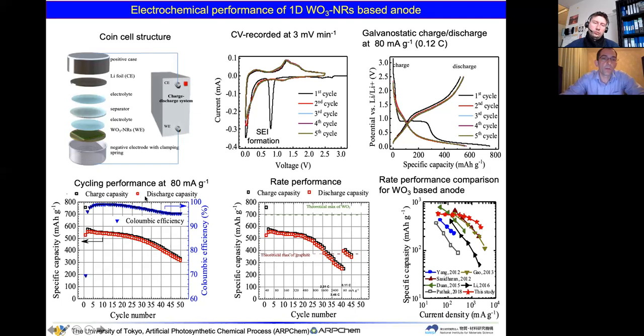The cyclic performance at this 80 milliamp per gram. So it's relatively a stable material during the cycle number. However, there is a small degradation rate. But this is interesting, okay? If we look on this graph, we can see that if we change the C rate to the smaller one, so this material is recovered.